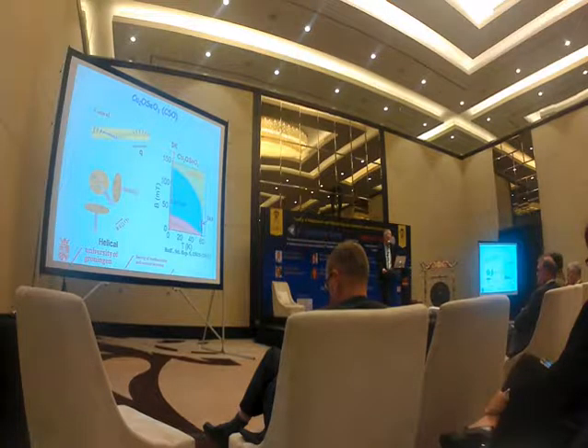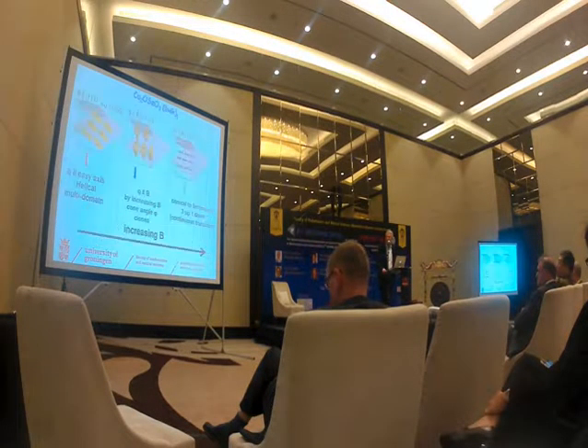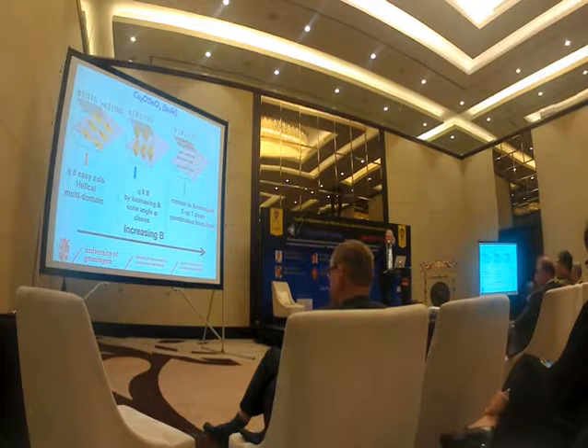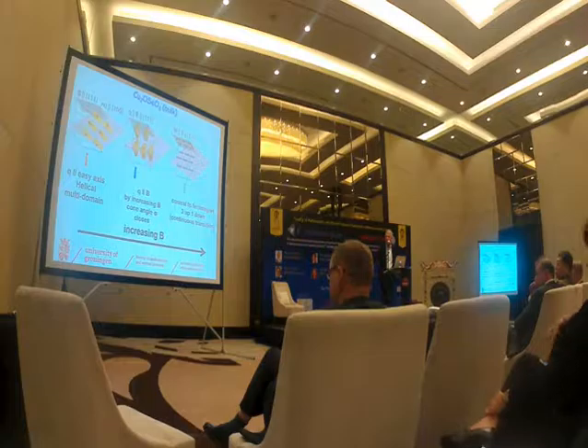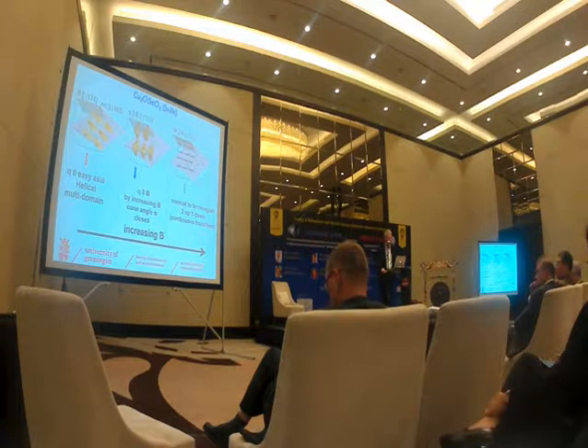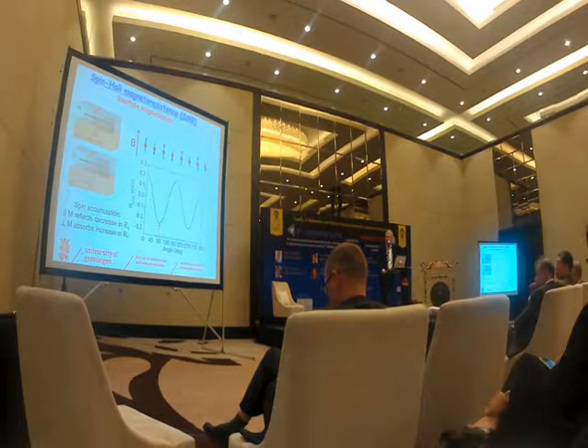And then what you measure is the field dependence of the spin states going from this helical state to the cone state to the fully aligned ferromagnetic state. You can measure then the magnetic resistance, as I indicated. On top of this copper oxide selenide, you deposit a layer of platinum.